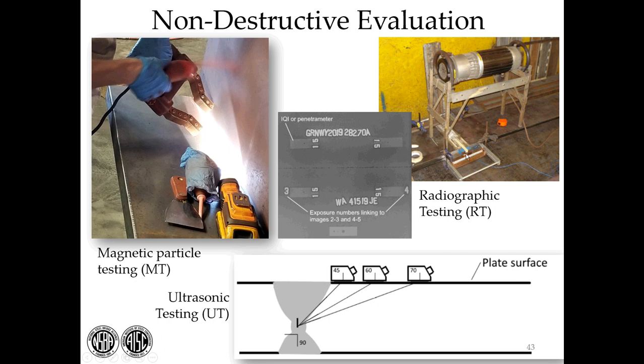Another process we use is radiography or X-ray. So here you see the X-ray tube. X-ray can be conducted with an X-ray tube or with a radioactive source. You see the weld here. Film or a screen is placed underneath. The X-rays are shot through the weld to the screen, and if there's any issue in the weld, it'll show up. So for example, in this particular radiograph, you'll see that there was a line of lack of fusion in this particular weld.